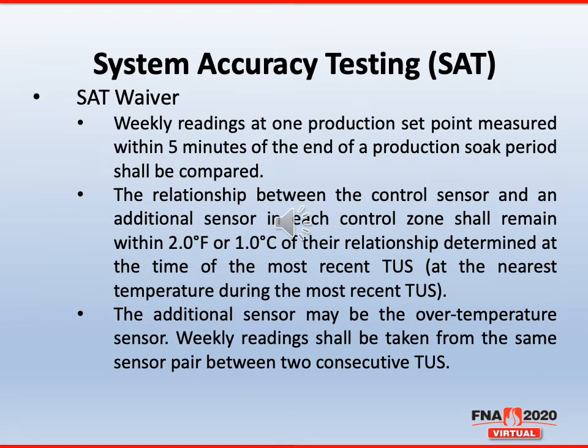Furthermore, the weekly readings that are required shall be done at one production set point measured within 5 minutes of the end of a production soak period and shall be compared. That relationship between the control sensor and the additional sensor in each control zone shall remain within 2 degrees Fahrenheit or 1 degree Celsius of the relationship determined at the time of the most recent TUS and at the nearest temperature during the most recent TUS.